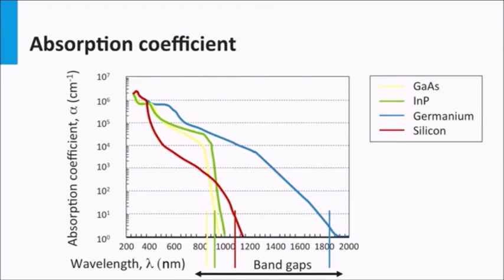Secondly, if we focus on the visible spectral part from 300 nanometers up to 700 nanometers, we see that the absorption coefficient of indium phosphide and gallium arsenide is significantly higher than that for silicon. This is related to the fact that indium phosphide and gallium arsenide are direct bandgap materials as discussed earlier. Materials with an indirect bandgap, like silicon and germanium, have smaller absorption coefficients. Only in the very blue part, below 400 nanometer, silicon has a direct bandgap transition.